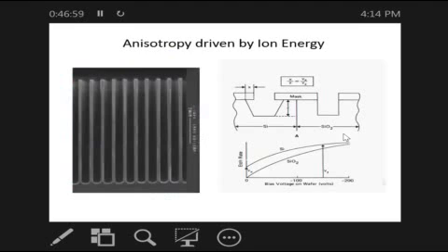Now this is one example of anisotropic etching. You see this SEM picture, right-hand side, there is a scale bar, a kind of measure. From here to here is 20 micron. In this case, the top opening of this structure is 20 micron, then this one is going to be around 4 to 5 micron. And the wall is less than 2 micron, even less. We want to keep this wall while we etch all the way down, more than 50 micron, around 60, 70 micron. We need to etch this deep.